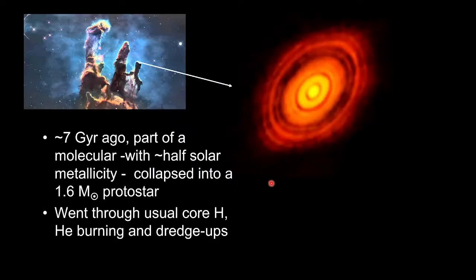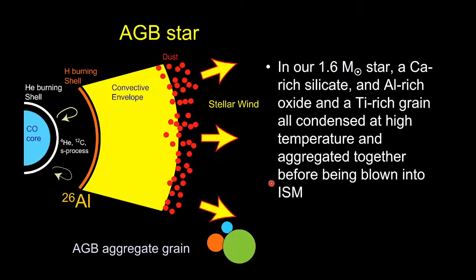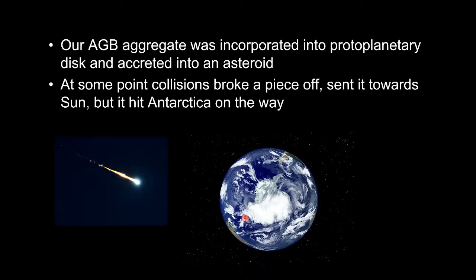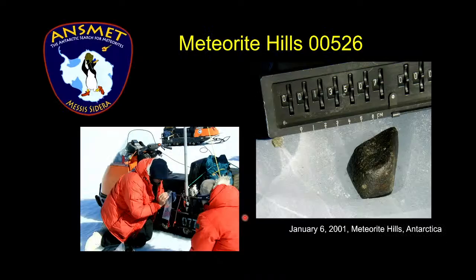Another low mass protostar, 1.6 solar masses, became an AGB star, did the usual thing, but in this case, 3 different crystals formed and stuck together in the outflow of this star: a calcium-rich silicate, an aluminum-rich oxide, and a titanium-rich grain. It was incorporated into a disk, did the usual thing, spent time, ended up on Earth on a meteorite that landed in Antarctica. This meteorite is called 00526. I was part of the field expedition in Antarctica in 2001 that actually collected this meteorite. And I took this photograph in January of 2001 of this meteorite sitting on the ice.